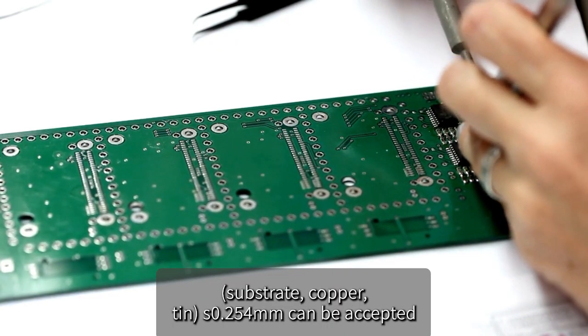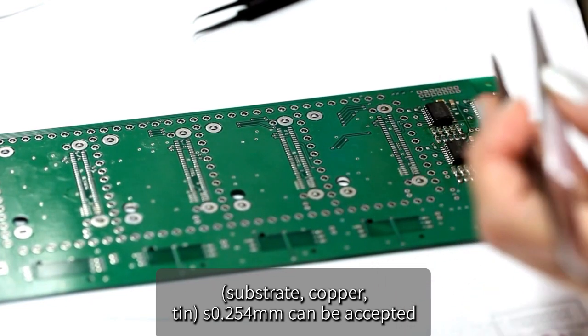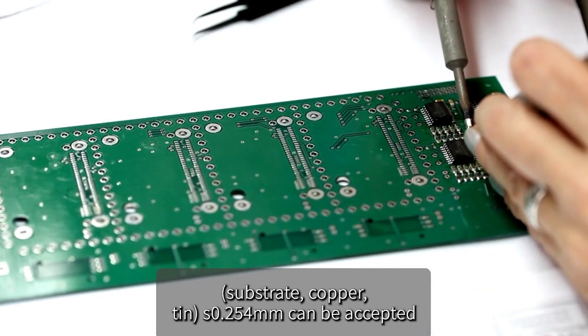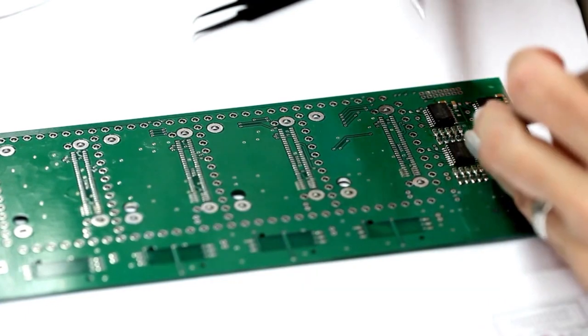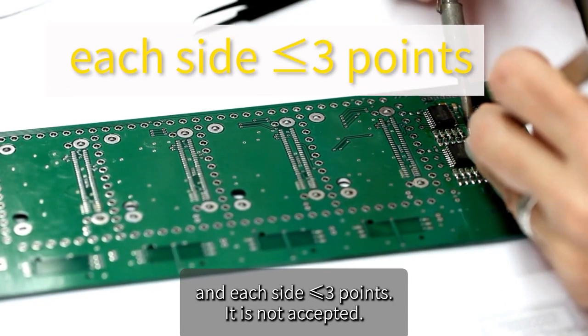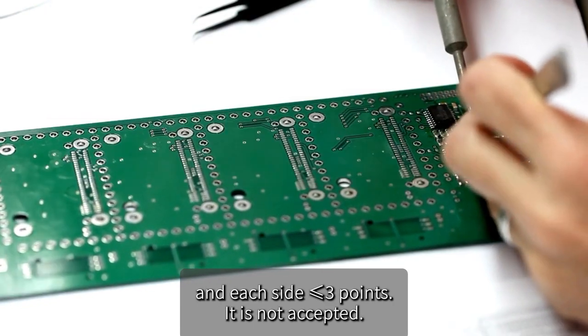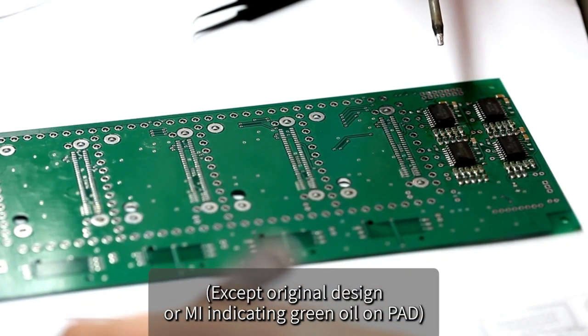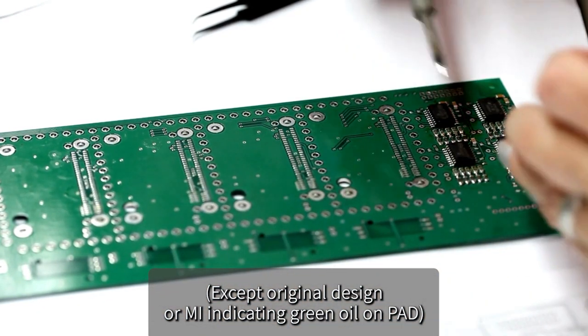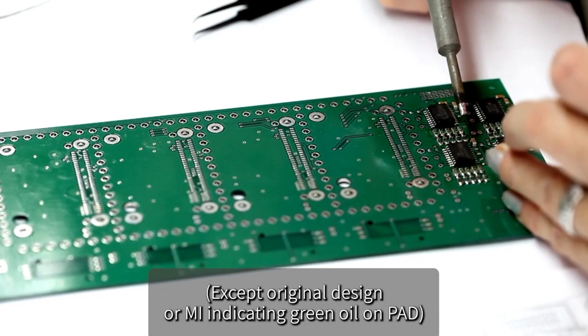Scratch-exposed bottom material, substrate, copper, tin, ≤0.254 mm can be accepted, and each side less than or equal to 3 points. Otherwise it is not accepted. Except original design or MI indicating green oil on PAD.